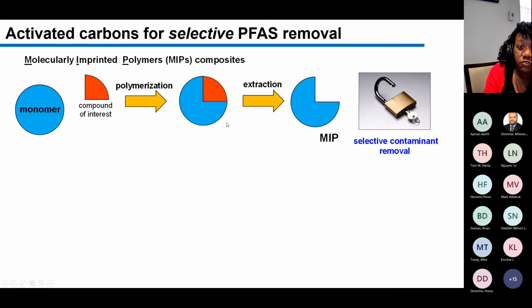And then you can do an extraction step at the end where you remove the compound of interest that you started with, and then you generate this kind of Pac-Man-like shape here. And this is the final molecularly imprinted polymer configuration. So the idea here is that you get a lock and key type removal mechanism where this particular polymer should only remove the compound that you started with. So that's how you impart the selectivity and the more targeted removal.